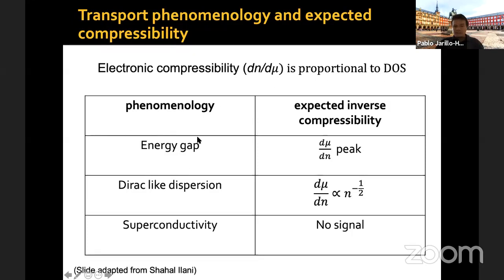If you have an energy gap in your system, dμ/dn is expected to be infinite because of the energy gap, or in realistic terms, a peak, a large maximum. If you have a Dirac-like dispersion, your density of states is proportional to the square root of density. Therefore, your dμ/dn is proportional to 1 over the square root of density. If you have superconductivity, because that does not lead to a signal in the thermodynamic density of states, then in principle, you expect no signal.